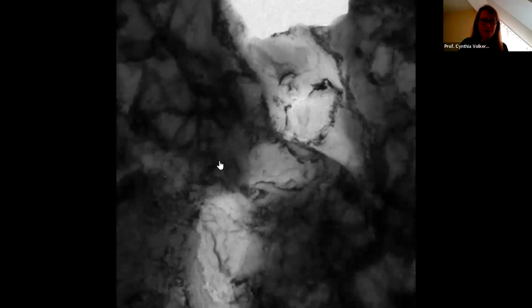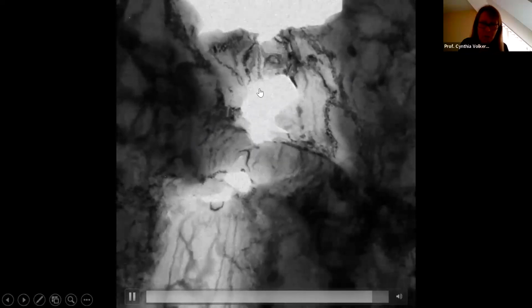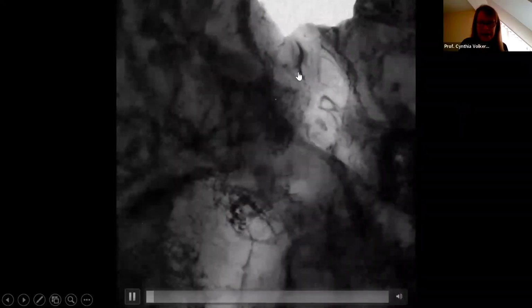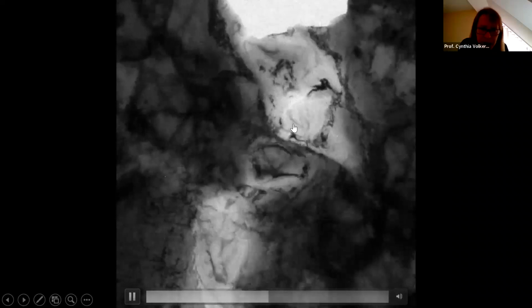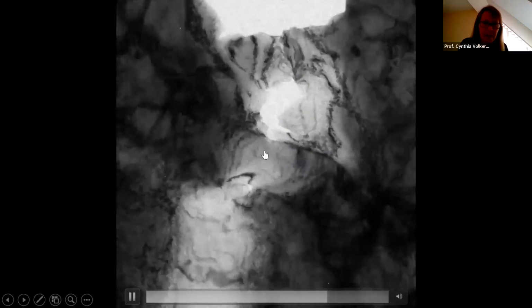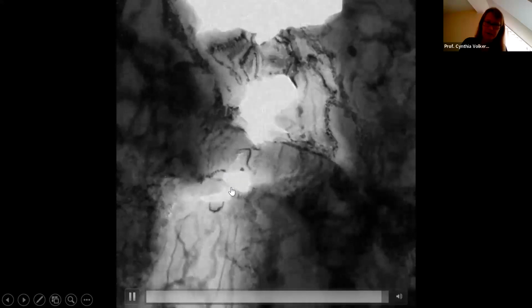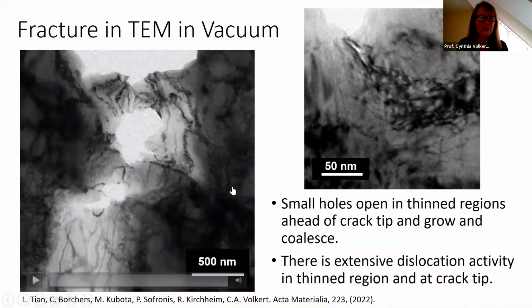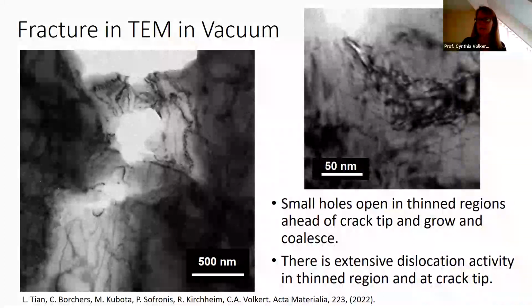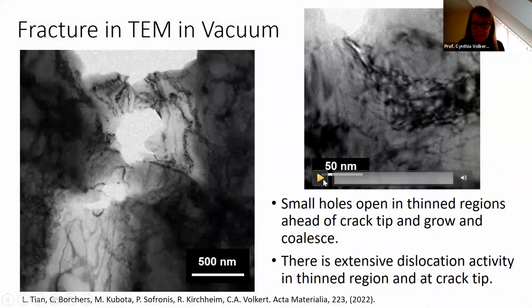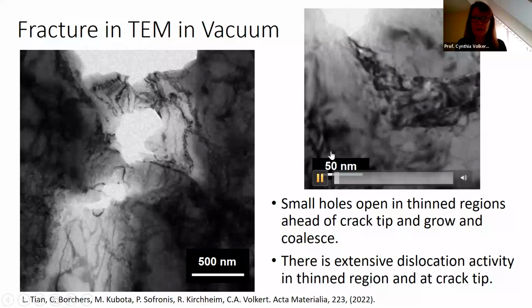You see contrast from bending contours. That's just simply from changes in thickness, or bending from diffraction. You see voids nucleating and opening up ahead of the crack tip. So here's a void opening here right now. And there'll be one opening further up down here as well. So there's a chain of voids opening ahead. And a lot of the features you see are bending contours, but there's also dislocation motion going on. So that shows you what it looks like.